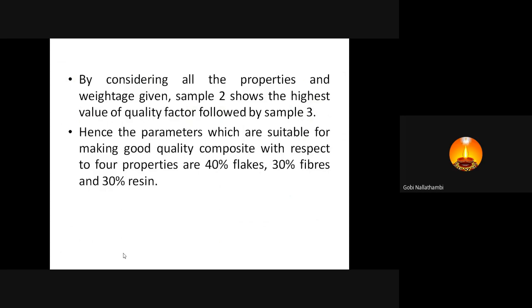By considering all the properties and weightage given, sample 2 shows the highest value of the quality factor, followed by sample 3. Hence, the parameters which are suitable for making a good quality composite, with respect to 4 properties: compression strength, tensile strength, impact strength, and also hardness, are 40% flakes with the given dimension, and 30% fiber, that is 36 mm fiber, and 4 linear. Then the resin is 30%. That gives the optimum property.